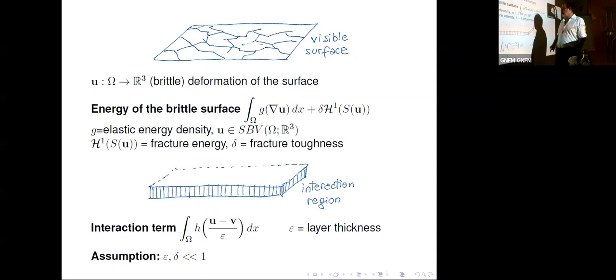Proportional with a factor which is called delta, which is the fracture toughness of the surface. And then you have an interaction region. So up until now, you have two unrelated variables. These are related by the fact that you have this thin layer, and you have an interaction term which depends on the difference, and so on the relative displacement measured on the reference configuration, the two-dimensional configuration.